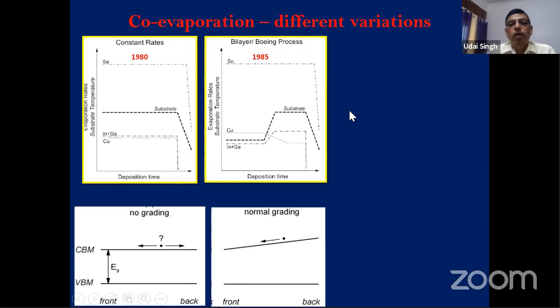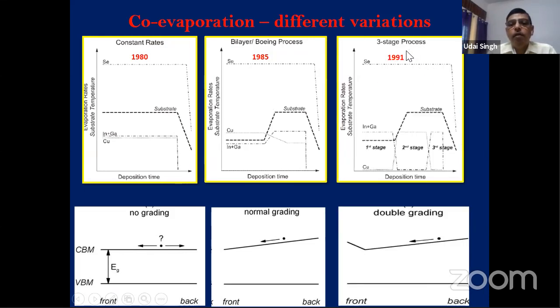This has gone on. But in 1991, NREL in the US discovered a 3-stage process. In this, the selenium flow is constant. Here the temperature is lower and there is no copper. Initially, they don't deposit any copper, only indium gallium. After a certain time, they increase the substrate temperature and increase the copper, whereas they reduce the indium and gallium. In the 3rd stage, again they raise the indium gallium and reduce the copper to 0. That's how they get a double grading structure. So it is possible to control the gallium gradient. This has given the best structure, the best device.